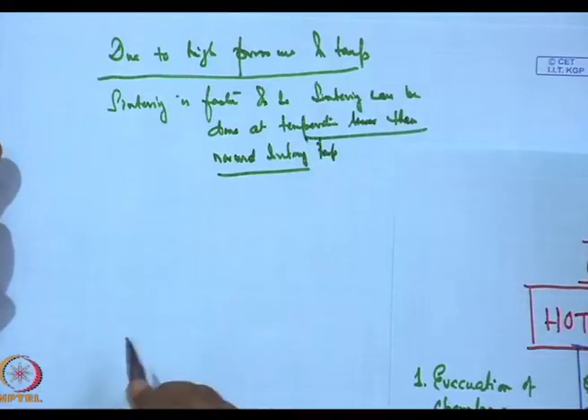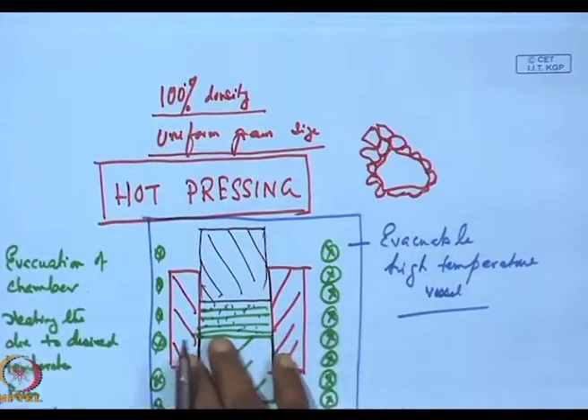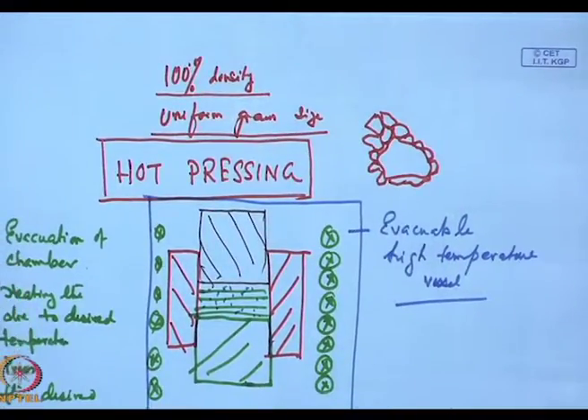And lower than normal sintering temperature. However, in spite of these advantages of hot pressing, we have severe issues in using a hot press. Firstly, whatever die material you use, it will have a thermal expansion. So during heating, the die will expand. The hammer, the anvil also will expand, and when you cool, they will contract.